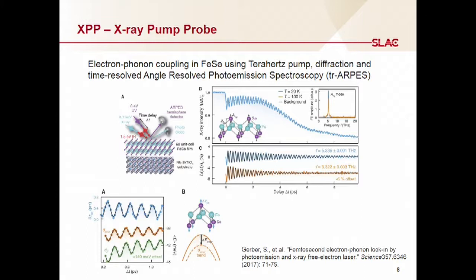These people were thinking that by doing diffraction, which looks at how the lattice vibrates, so these are phonon modes, and how that couples with the electron energy states, perhaps that can tell us something about why these are superconducting. What they found was that if you excite it with a terahertz pump, it excites the selenium atoms, and they vibrate, creating this phonon mode.